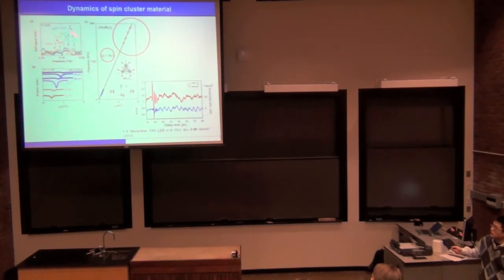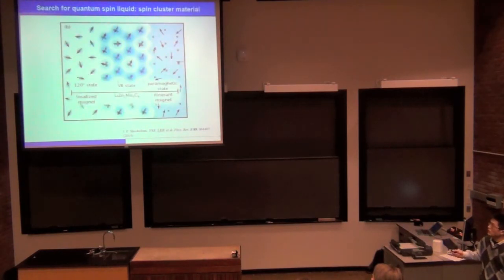So this is our data in the frequency spectrum, and you can see the Terahertz really provides some very nice data in this high field and high frequency range. Although traditionally ESR data is measured by microwave cavity measurement, but as you can see, they provide really limited frequency range. And when we put in our Terahertz data, we increase the accuracy of the obtained g factor by at least 1 order of magnitude. And from our measurement combined with this low field microwave measurement, we get a very good idea of the g factor. It's very close to the free electron g factor, which is 2, and it doesn't show any anisotropy. So you can see the spins in this system really behave like a Heisenberg-like spin 1/2 particle. And as a result, this valence bond state is a really accurate description of the system.